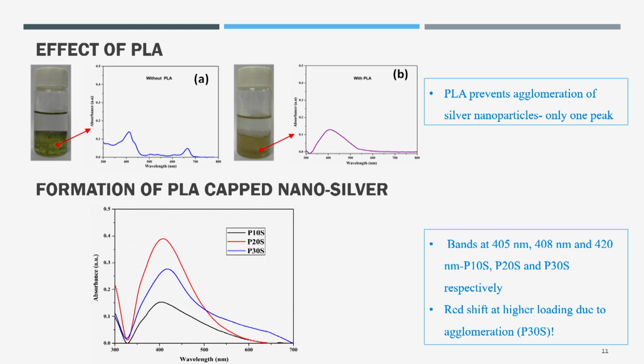I said that silver particles have catalytic activity, which can be enhanced by PLA. This is the first evidence for that. Without PLA, you can see absorbance on the y-axis and wavelength on the x-axis, so immediately you realize that it is a UV visible spectrum. And how many hills are there? Two hills are there, though we have only one particle, silver in the solvent. Each hill is a representation of some transition, so two transitions are happening there. It means silver is in two states: somewhere silver is agglomerated, somewhere it is not agglomerated. So that's a clear-cut indication.